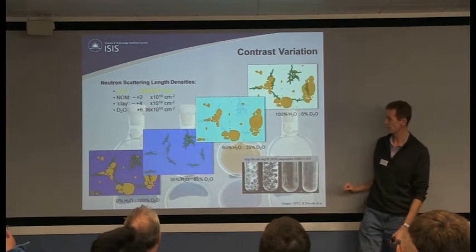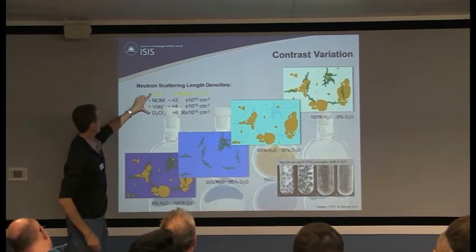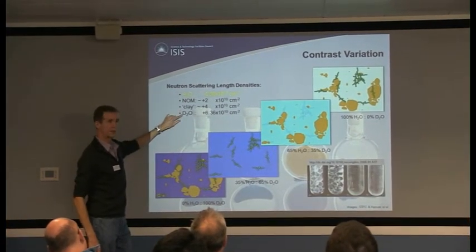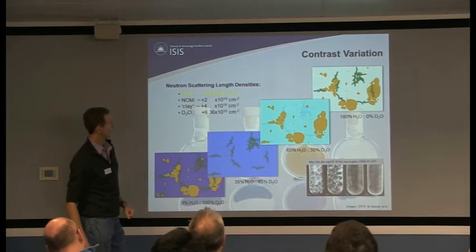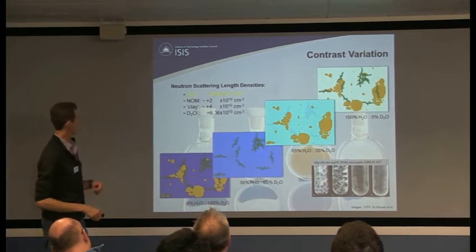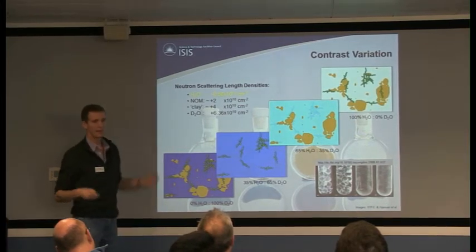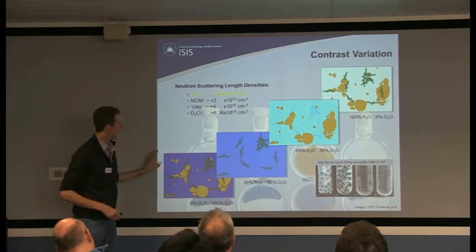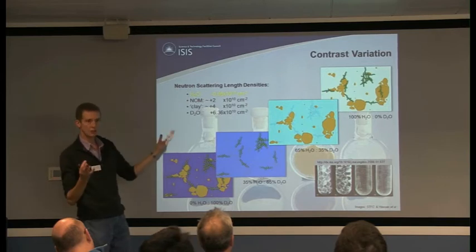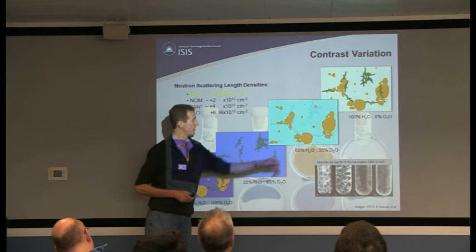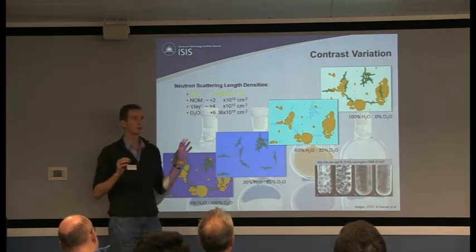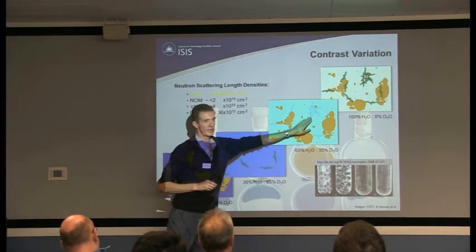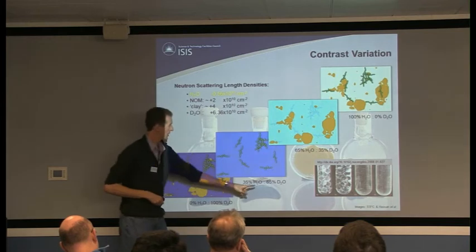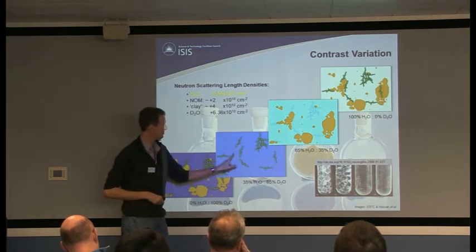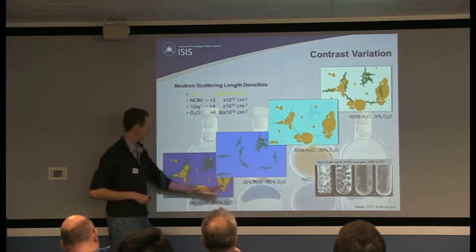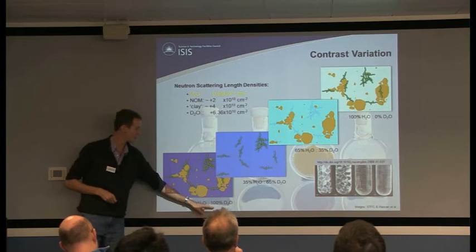We can do exactly the same thing with neutrons, using mixtures of normal light water and heavy water. Take a generic environmental sample with something mineral, which I've called clay, and something that's natural organic matter-like. Look at it in normal water, you'll see everything. Get to about 35% heavy water, and you're doing what we call matching out the organic matter, so all you see is the mineral. Add a bit more heavy water, and now you match out the mineral so all you see is the organic matter. By the time you get to totally heavy water, you see everything again.